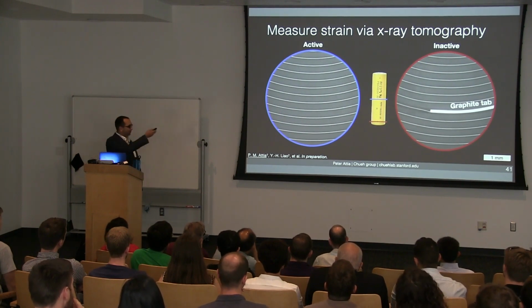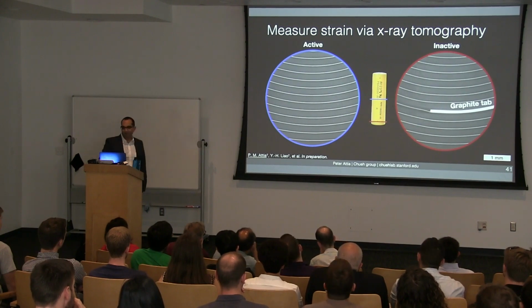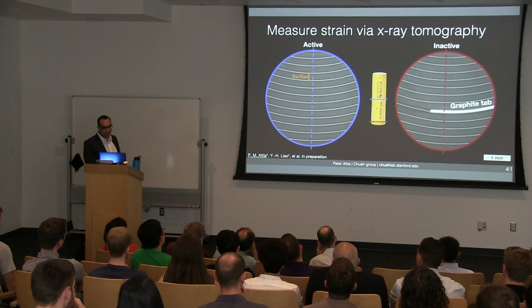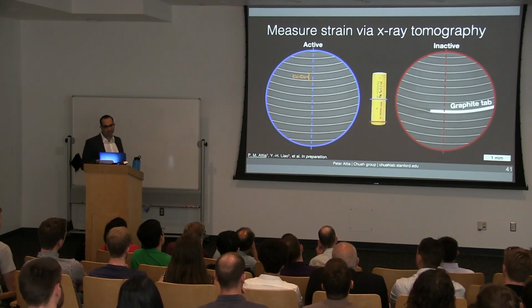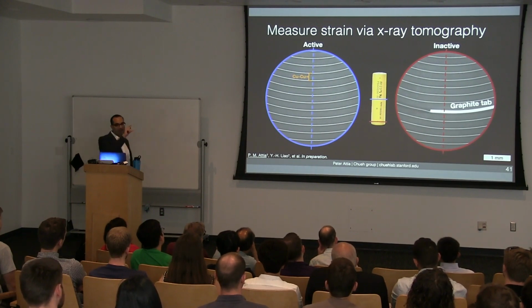Now visually, these two electrodes are pretty similar except for the tab. But we can actually quantify the strains via tomography. So what we can do is take a line scan. And because the copper current collector is so bright, we can easily detect it. So measuring the copper-copper distances provides an easy way to measure the stack thickness.